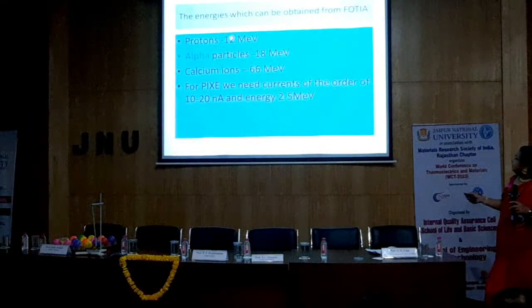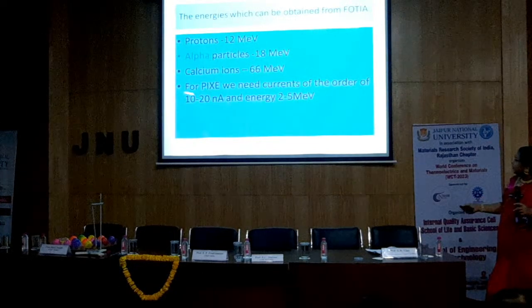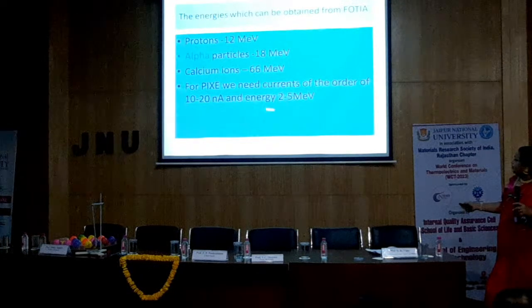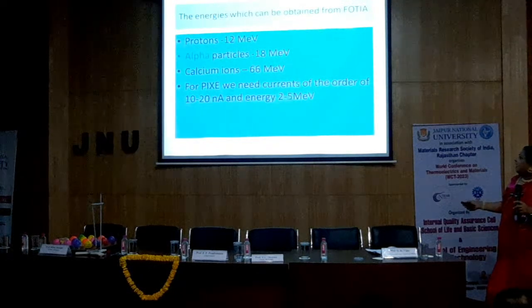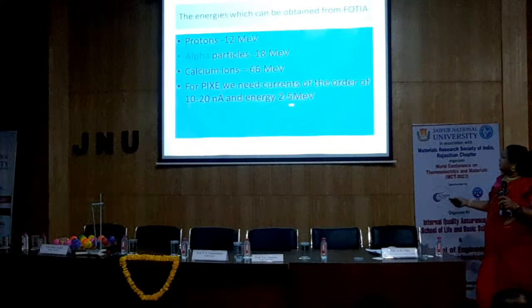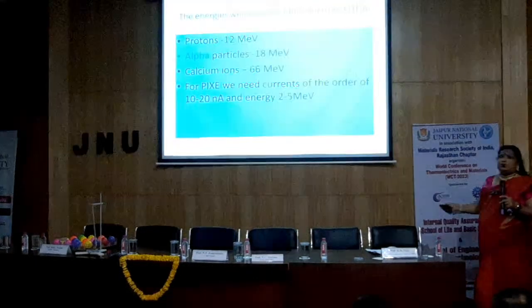So here the energy used is 12 MeV. For alpha it is 66. For PIXE we need a current of 10 to 20 nanoamperes, energy 2 to 5 MeV. Otherwise your samples will get burnt. So it has to be on the lower side. I have worked with 3 nanoamperes also, 7 nanoamperes also. And the energy I used to work with was around 3 MeV.